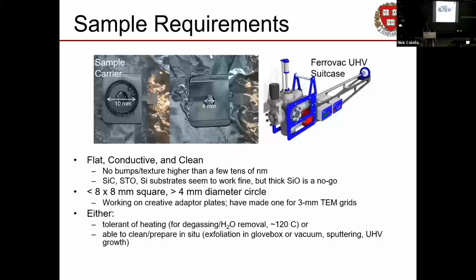And so under UHV conditions, we got to get that water off because we don't want to see it in LEEM. We got to heat up to at least 120 degrees, usually more like 300 or 400 degrees. If your sample doesn't like getting that hot, then we got to find another way to clean it. And most people's samples don't like getting that hot. It's not great for most materials to get that hot. So we have other ways of dealing with it and getting around this problem, but it's something you have to factor in if you want to do this one.